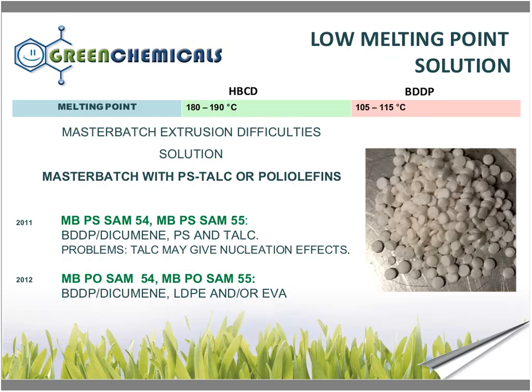Now we come to the bad points of BDDP. One is the low melting point. BDDP melts at 110 degrees, and when it is mixed with dicumene, it is even lower, around 70 degrees. And as Ethel has told you, to bring the product inside the XPS board, we need to produce a master batch, mixing the powder with a polystyrene carrier.